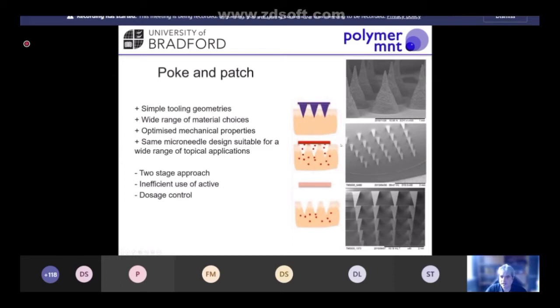And then we can apply a topical treatment like a cream or a liquid onto the surface of the skin. And that's then able to flow through those holes and diffuse into the underlying layers and administer your dose. Or what you could do is you could have a dissolvable patch or a transdermal patch as well that you just stick over the holes that you created, and you get a similar diffusion of that active pharmaceutical ingredient. So it's a really, really simple approach.